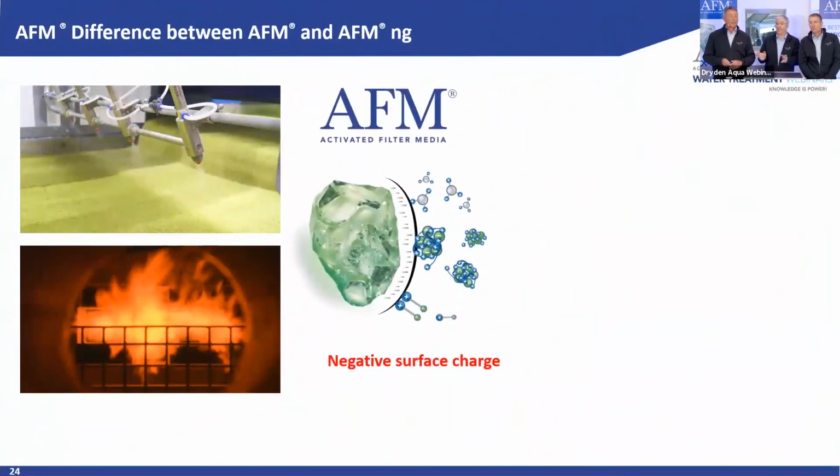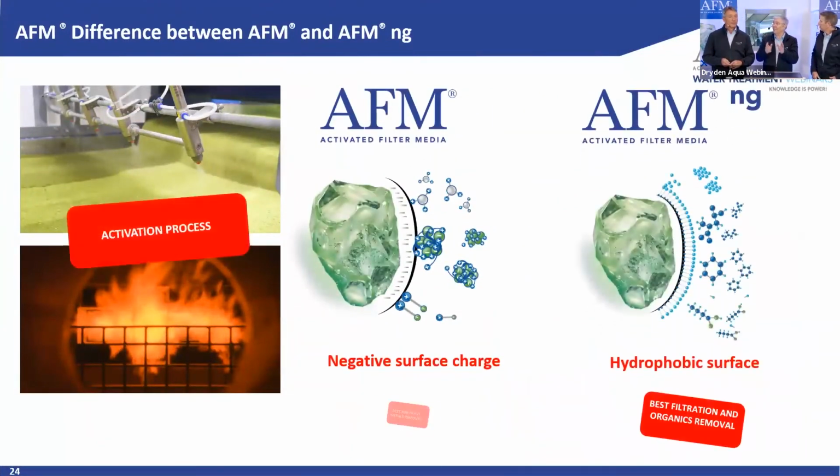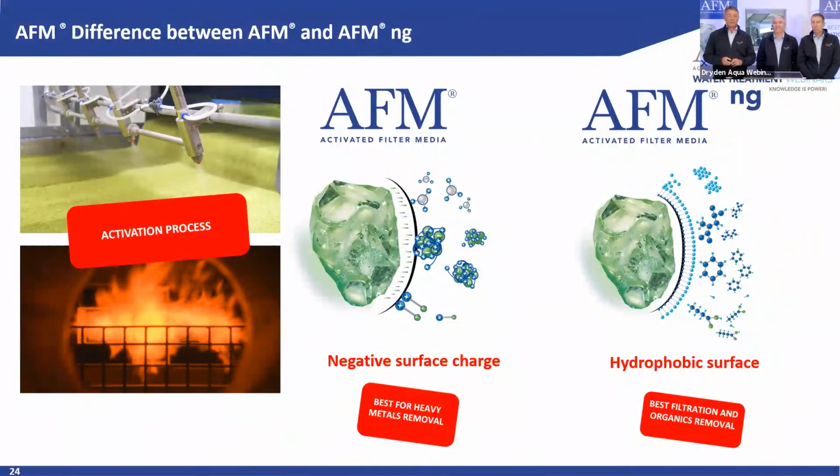Maybe to mention that even if it's hydrophobic, it's not floating, so we have really control over the production process. That works perfectly as a filter media. We also write this in our manual: you have to treat it a little bit like activated carbon. You should put it in water and leave it there for 24 hours before you make your first backwash, because in the first few hours a few particles are floating. It's also normal that there is a little bit of fines that you will lose in the first 2-3 backwashes. That's kind of normal.